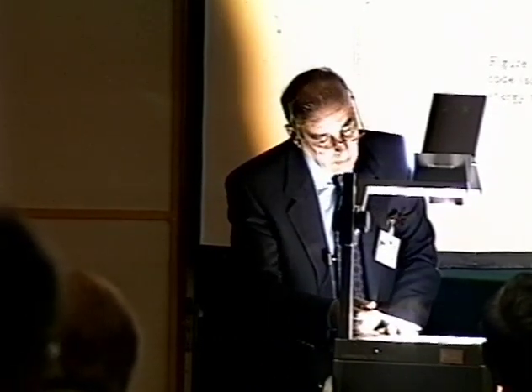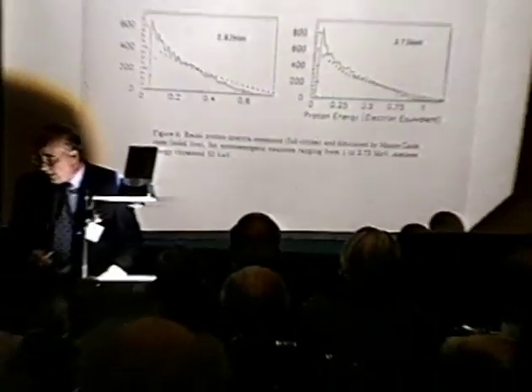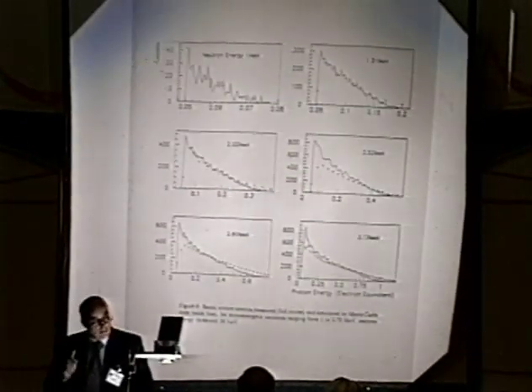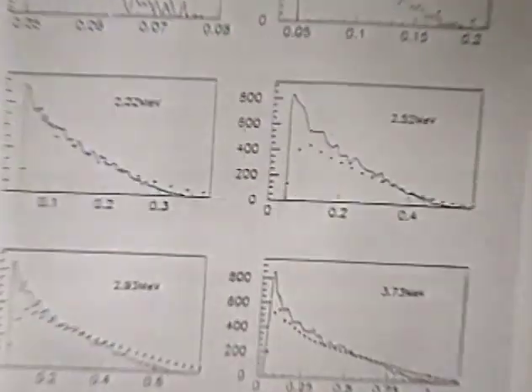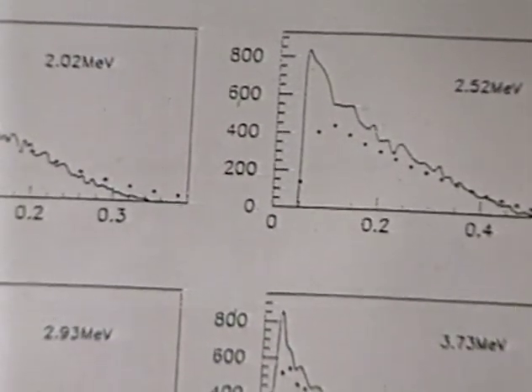For the comparison of the simulated and real signals, we have first of all compared the spectrum achieved on the first detector, the scattering detector, the liquid scintillator detector, with the calculated one. And you see the points represent the Monte Carlo simulation, and the continuous lines represent the real spectrum. And there is a nice fitting, which means that the program, the Monte Carlo simulation, was good, and the response of the liquid scintillator spectrometer was all right.